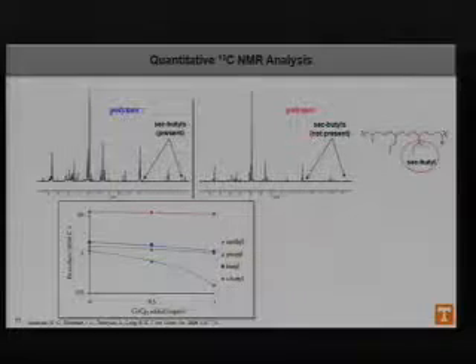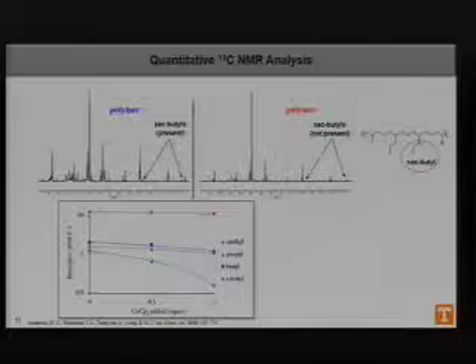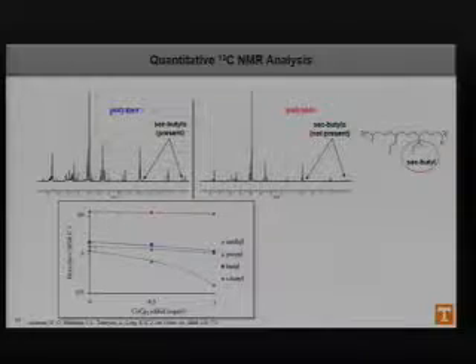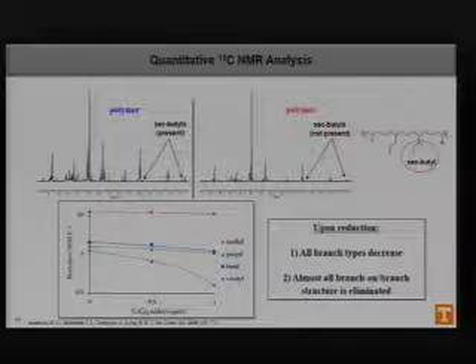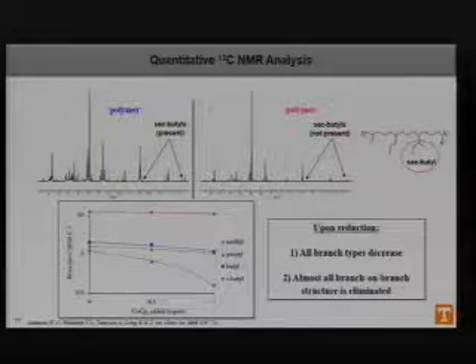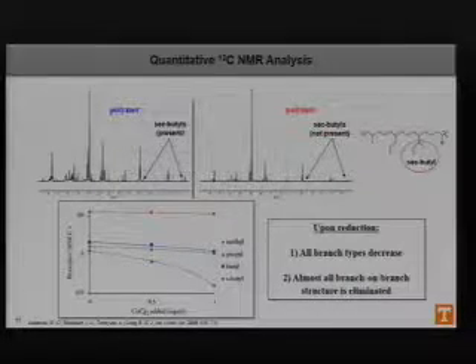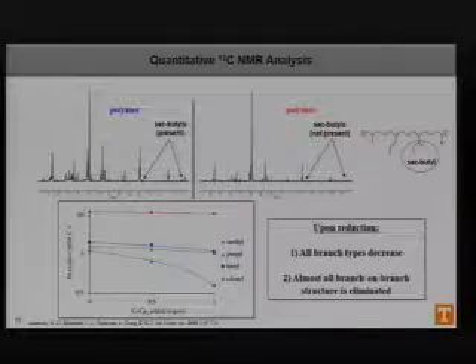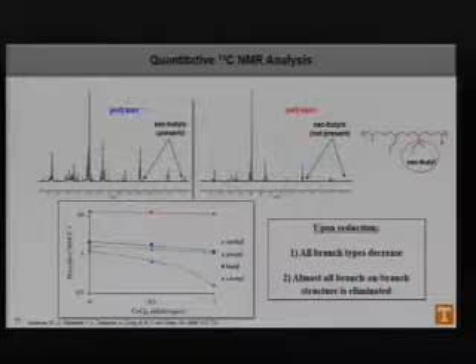If we take a look at the other types of branches that can form, just a few are listed here, the methyl, propyl, butyl, and also the sec-butyl. All of these branches actually tend to decrease as we increase the reductant that's been added. So all in all, we were able to decrease all of the branching types and specifically almost eliminate the branch-on-branch structure, which is the beginning of the hyperbranch topology where you can lead to extremely flexible and adhesive-like materials.